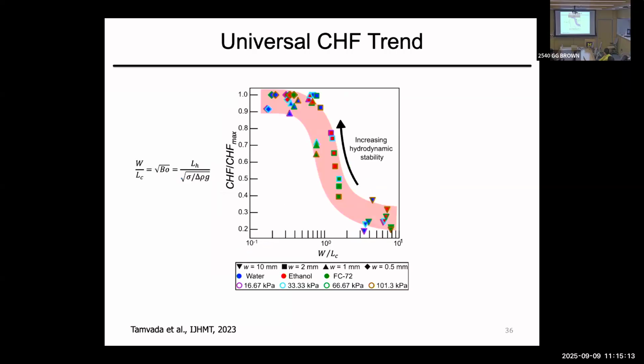So we said, okay, if you take all those data, get all the CHF values, and divide them by the maximum CHF that we measured, regardless of the heater, the fluid, or the pressure, it comes out on this beautiful curve, which starts from where the Zuber limit is. We believe this is associated with the 10 by 10 millimeter surface. Each time we narrow it, it's a different hydrodynamic state. It's higher than Zuber, but it's still a hydrodynamic limit. And ultimately, you get to a number that you can never go above.